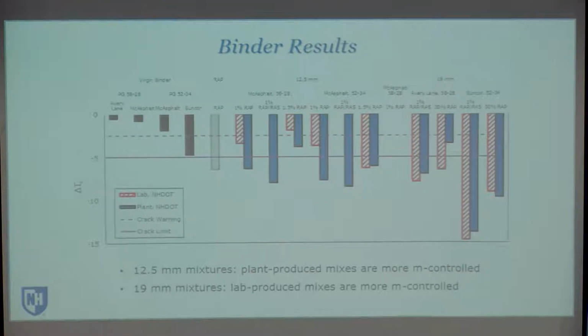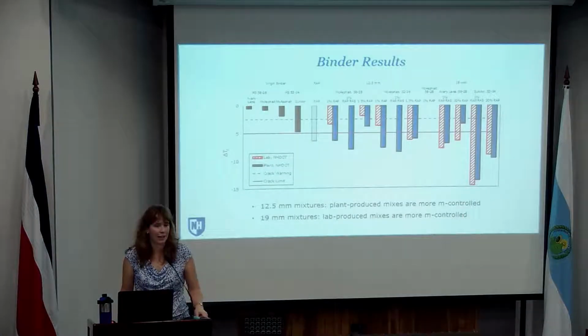Okay, the one that does stand out is that Suncor. Okay, that Suncor binder, as the virgin binder itself, if you looked at the delta TCR, identified itself as being a problematic material. Okay, turns out that that material did have REOB in it. Okay, not a surprise after we actually went through the testing.